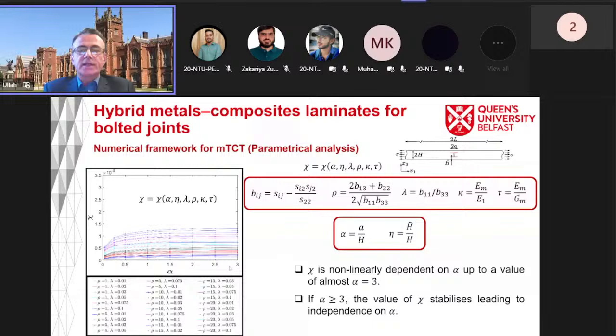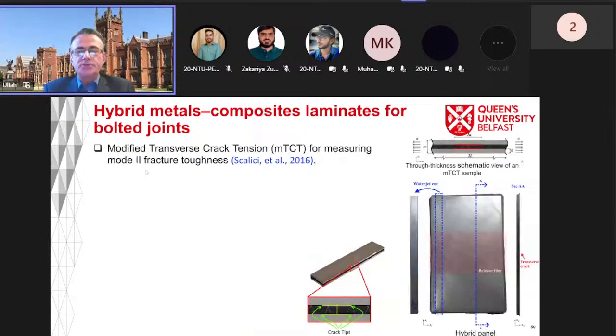So based on this, we prepare our experimental sample here. In our case, we have created this sample, as you can see here. So we have composite in the middle, and then we have two steel on both sides. For the composites, we are using this M79 UD600 prepregs. And for the steel, we are using the carbon steel here. And to bond the steel with the composite, we are using this Hexbond 679 resin. And these are the different dimensions of the samples here. So the sample size is around 250 by 15.